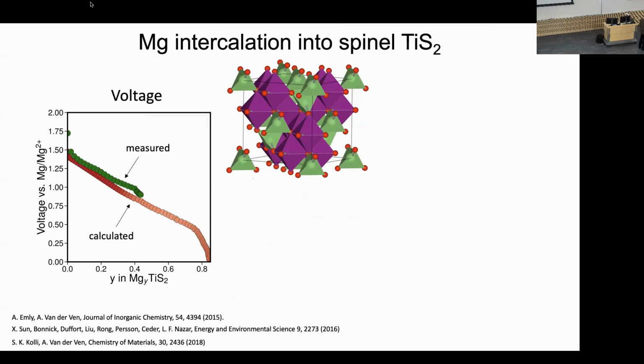About 10 years ago, there was a lot of interest in replacing lithium with magnesium. Magnesium is 2+, so that means you can get more charge in and out per cation. So there's a lot of interest there. And so we wanted to see, what if instead of putting lithium into this compound, we insert magnesium? What kind of voltage curve would we get? We calculated the voltage curve using these techniques, only allowing for magnesium vacancy disorder. That's the only degree of freedom that we considered. And we got this red curve over here. You can see you can get a little more than 0.8 magnesium per titanium sulfide unit into this crystal structure.